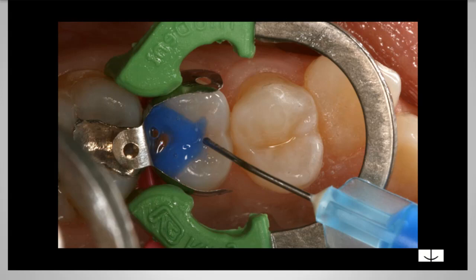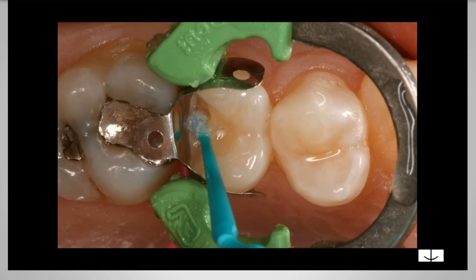Some people like to use Composites. I use Cavity Cleanser by Bisco. It's a 2% chlorhexidine solution. And chlorhexidine has been shown to decrease bond degradation within the first 6 months of that bond setting. We know that different things, moisture and things, can degrade the bonds in the first 6 months, and that can lower bond strength. And chlorhexidine has been shown to inhibit bond degradation, and that's one of the reasons why I use that as my re-wetting agent.